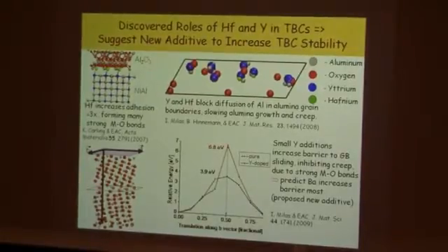We also showed that yttrium, for example, and actually hafnium does it too, this is showing an energy as a function of sliding this grain with respect to this grain. What we showed is if you don't have yttrium around, you have a certain profile shown in black, and you can essentially double the barrier to sliding by just adding a little bit of yttrium at this interface. And we know that yttrium actually does get to this interface from experiments. So this is, again, a way in which we tie what we do to experimental work.